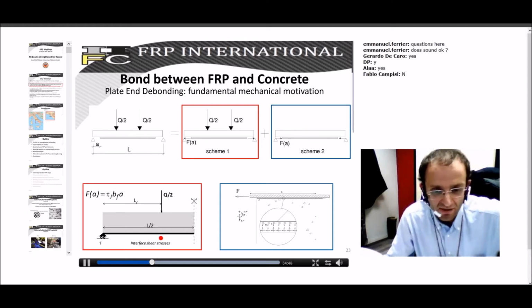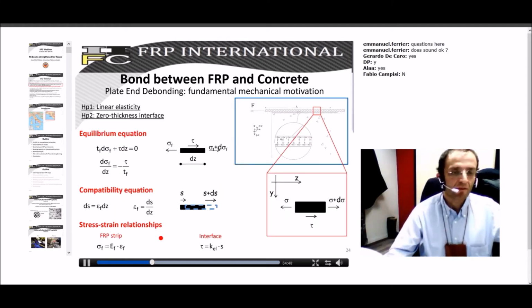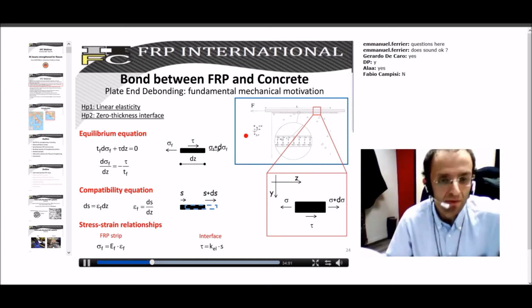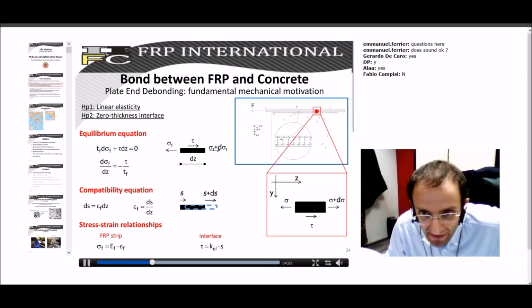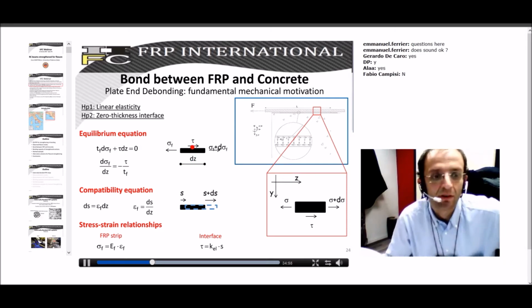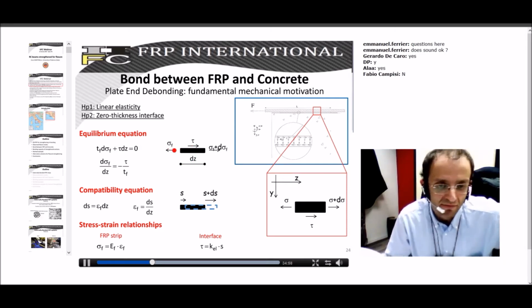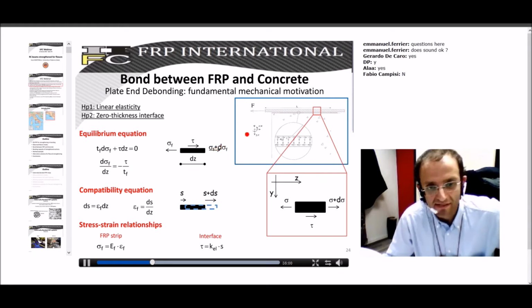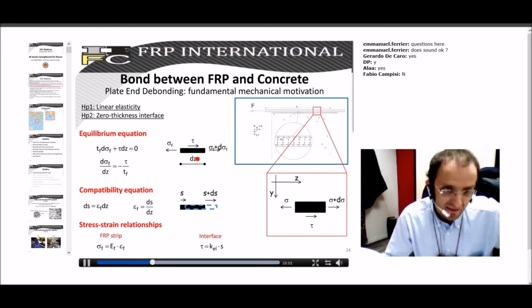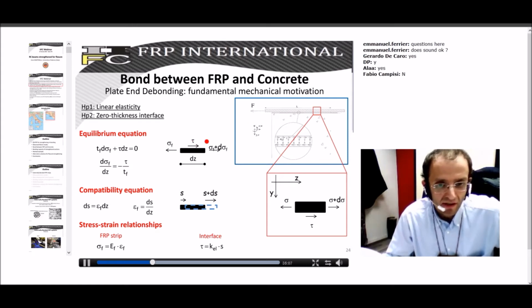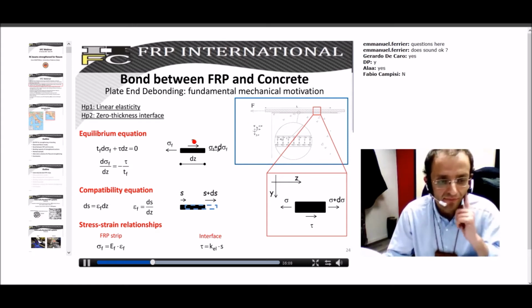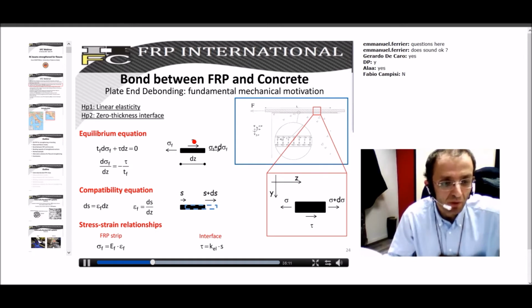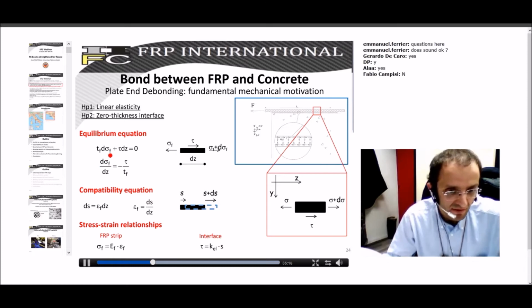So let's go ahead on this. We can write a few equations. We can write an equilibrium equation. If you consider a segmental element dz of the fiber, you have a sigma F on the negative face, sigma F plus its variation on the positive one. And these are in equilibrium with the interface shear, the interface bond stress tau, which is developed through the z. So you can write this differential equation. This is the indefinite equilibrium equation.